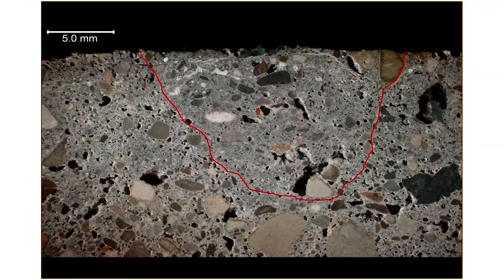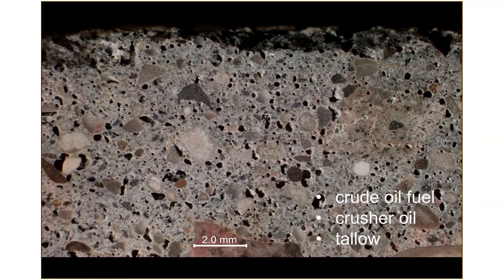Now here's again a cross section under higher magnification. Note all the little bubbles. This concrete looks practically air entrained, and this could be mistaken for a very recent concrete pavement. I mean, a lot of concrete that's going in in Minnesota, Wisconsin, all through the Great Lakes, all through the frost belts of the United States, this doesn't look like that bad of an air content that is purposely entrained, either using a natural Vinsol resin or a polycarboxylate, newer synthetic air void system that we put in concrete to produce freeze thaw durability.